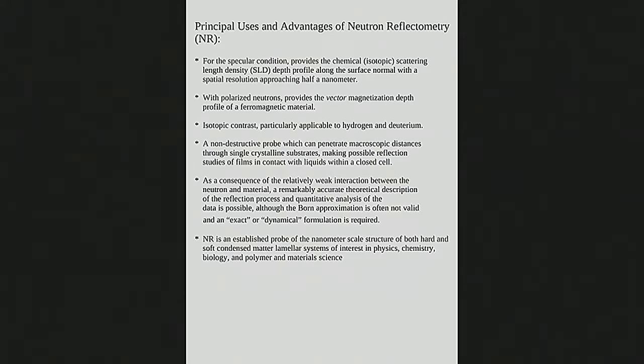What's different about reflectometry is that neutrons and X-rays, when they scatter from materials, are very weakly interacting probes, making analysis of scattering relatively easy compared to, for example, electron diffraction. However, a little bit paradoxically, at very low momentum transfers at low Q, the scattering is so strong that below some particular critical angle of incidence, every single neutron and photon is reflected. So it's extremely strongly interacting in that particular geometry, and we have to change the scattering theory a little bit for how we deal with the lowest Qs.